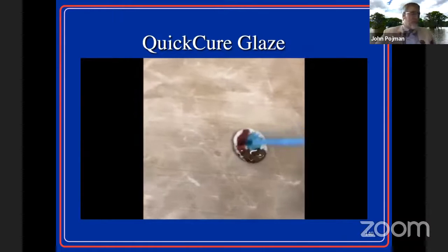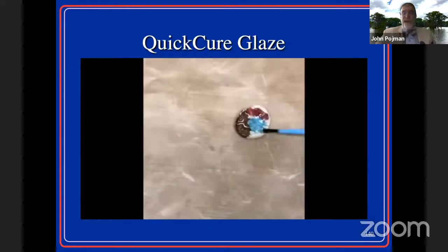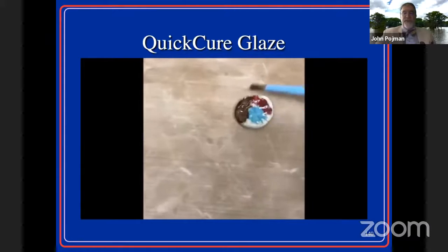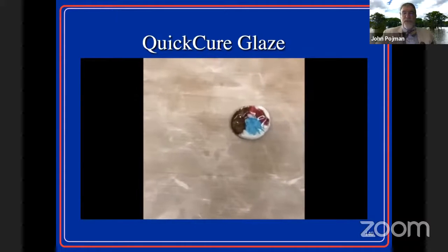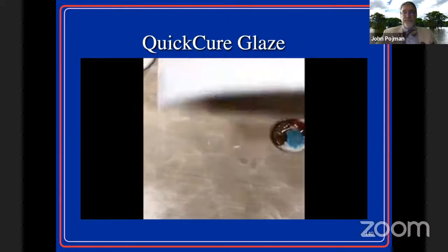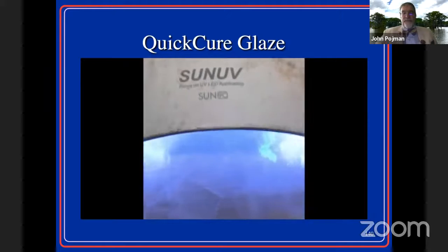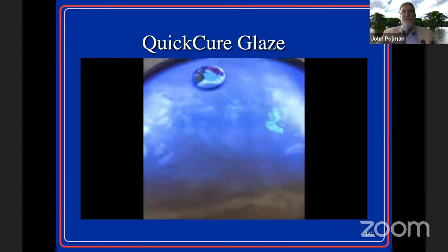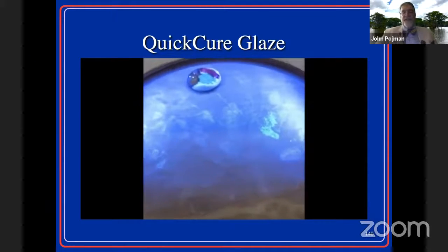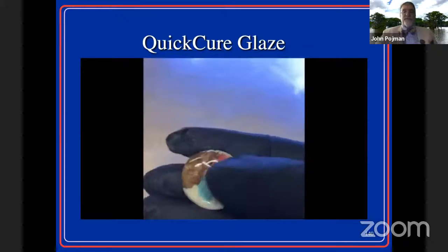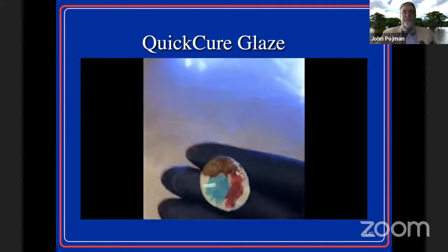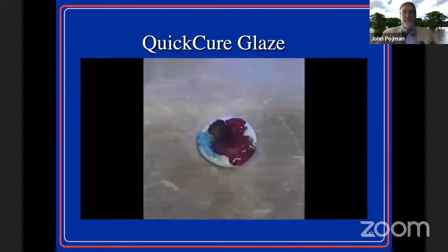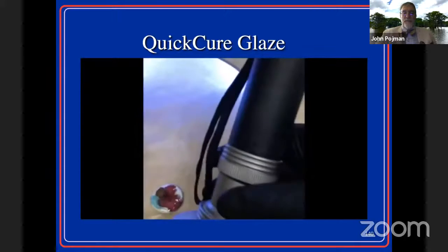And I had seen people use materials that required hours to dry. And I said, what's the point of a fast curing sculptural material if your coating takes a long time? You can use a 395 nanometer nail lamp. This is what's used in nail salons to cure coatings for fingernails. That coating is water resistant and a glaze, using a handheld.